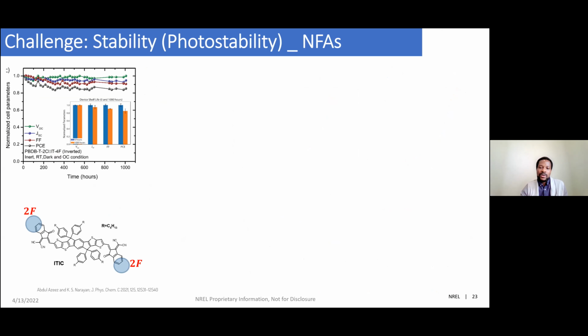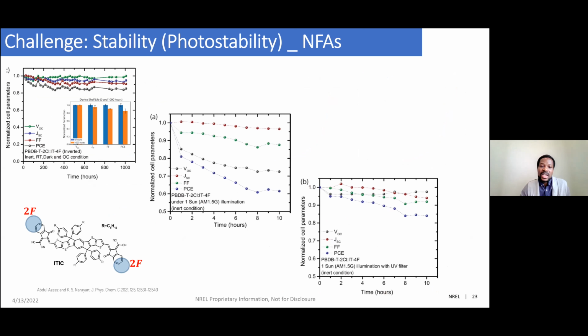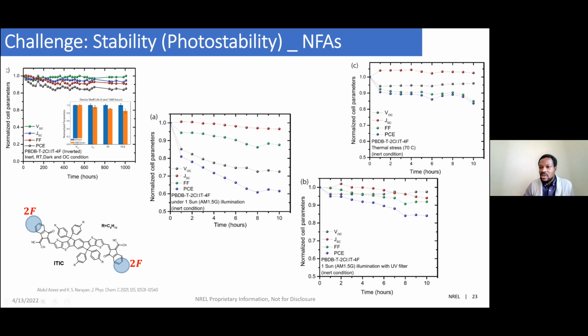But when you leave the realm of projection and you come to real experiment, you can see that shelf lifetime for the work done by Abdulaziz was kind of okay-ish, over 1,000 hours. But when you start exposing them to the sunlight, everything goes out of the window. This also shows that in this type of devices, the non-fullerene are not immune from the UV aspect of the degradation. So when you filter the UV part of the light as shown here, you can also recover your photostability. And then also thermal stability has been shown to be also a problem for this type of devices.